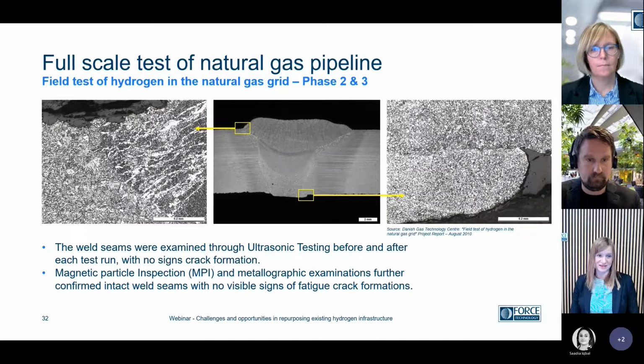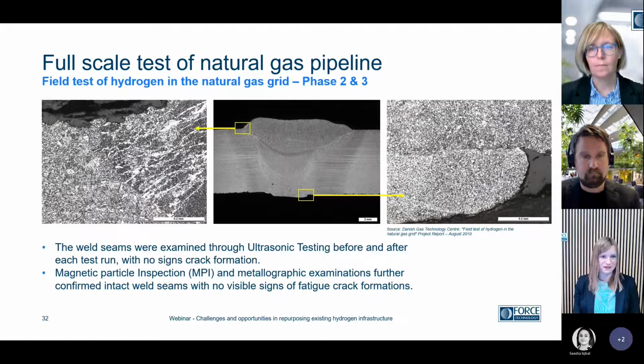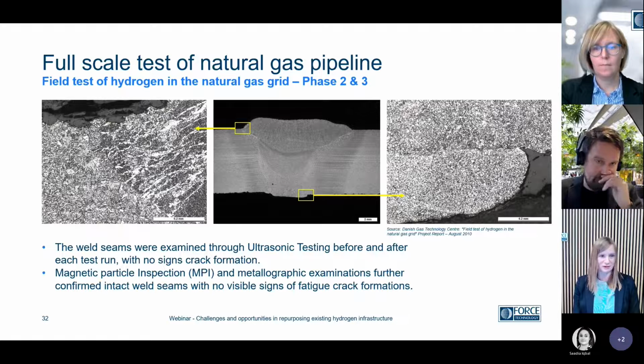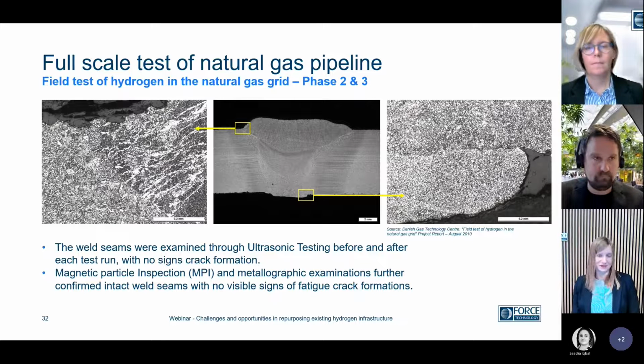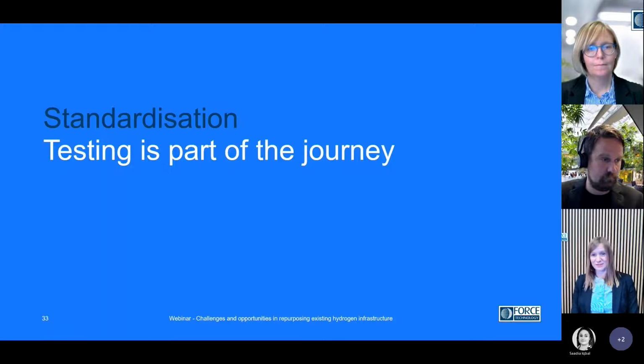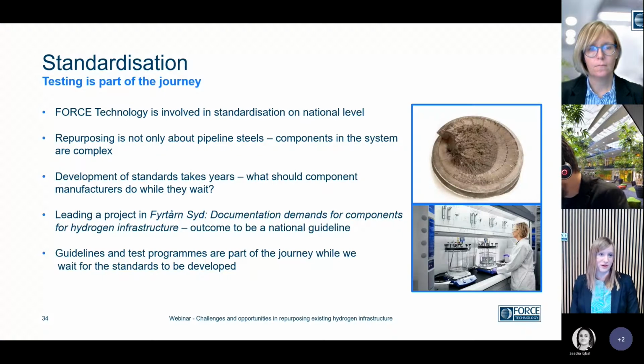UT, ultrasonic testing, and magnetic particle inspection were performed as NDT methods, and then metallographic cross-sectioning showed the weld here, and typically we would see cracking in these transition areas in the heat-affected zones. But looking at higher magnification, you can see that there is no crack initiation at all. And that's just another good sign that repurposing is actual. It's coming. And tests like these may help the green transition, but the hydrogen industry lacks standards. And we know that testing is going to be part of this journey.